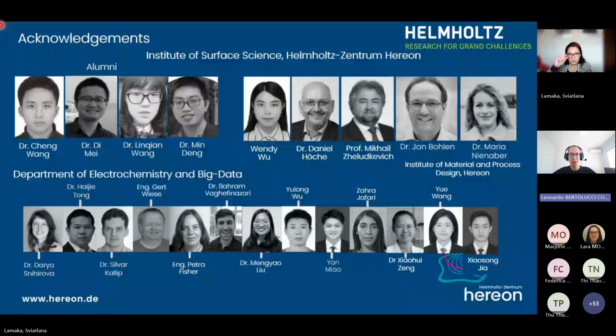I'm sorry, we are at the top of the hour, but there is time for one last question. Is it possible to measure cathodic and anodic areas undergoing uniform corrosion? Yes, for as long as corrosion is uniform, of course, and I think I had some examples there. So yes, you can measure this both with SVET and with pH, for example. But the thing is that for most metals, the corrosion is not uniform. Whenever it's an alloy, it's very often microgalvanic corrosion, and then the areas of anodic and cathodic activities are located on the sample. But yes, of course, local techniques are for distinguishing between anodic and cathodic activities at rather high resolution.